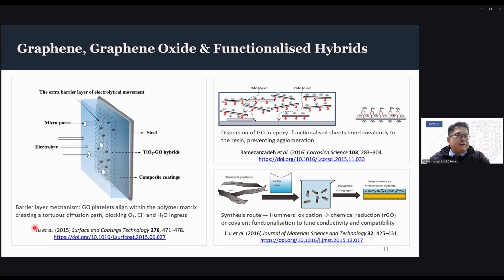The early efforts using graphene directly on mild steel involved the seeding or growth of graphene on exposed metal surfaces. So they weren't really used as coatings—they were just people trying to deposit some seed and then see if the graphene or graphene oxide flakes could actually grow, hoping that if it grows, it can confer some kind of corrosion protection to the mild steel surface.